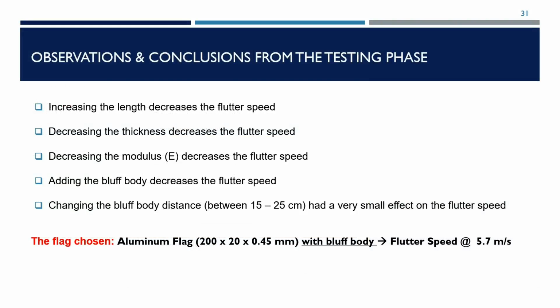What we can conclude from our test is the following. Increasing the length decreases the flutter speed. Decreasing the thickness decreases the flutter speed. Decreasing the modulus decreases the flutter speed. Adding the bluff body decreases the flutter speed. Changing the bluff body distance between 15 and 25 centimeters had a very small effect on the flutter speed.